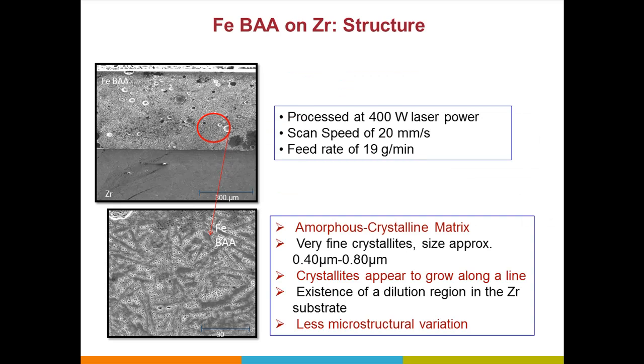And this is on zirconium. Again, this is not an easy substrate to work with, but we can actually put a bulk amorphous alloy coating on zirconium to show that it can enhance the corrosion resistance significantly.